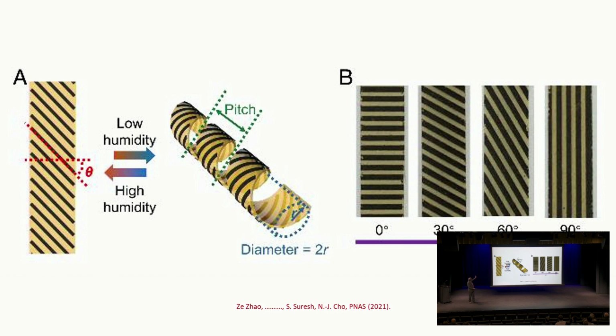So we decided to print lines on it. When you print lines on a piece of paper that is sensitive to water, what you find is there are different variables. The angle of the line with respect to the orientation of the paper, and the spacing of the line, so those are two things. Theta is the angle with respect to a reference coordinate, and then you have the pitch if it curls. So now let's see what happens. On the right-hand side, you have 0 degrees, 30 degrees, 60 degrees, and 90 degrees.